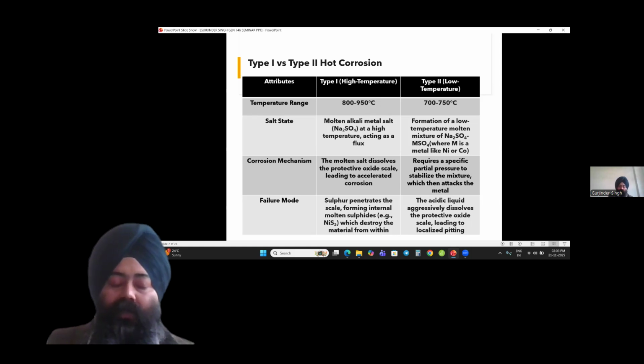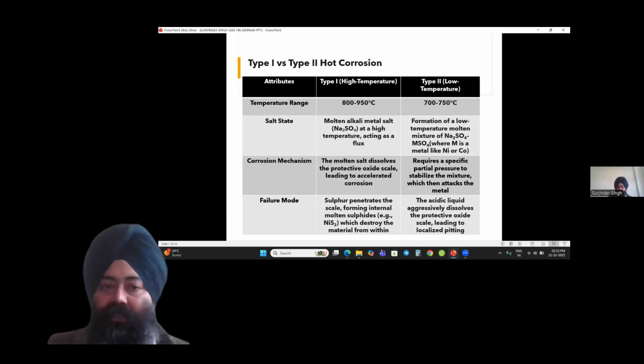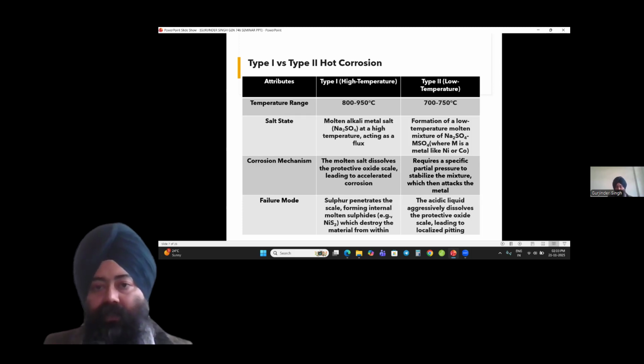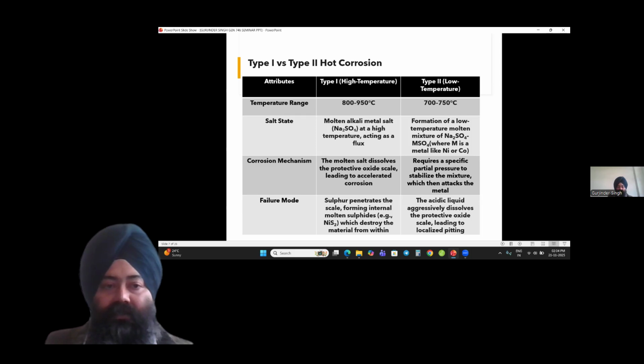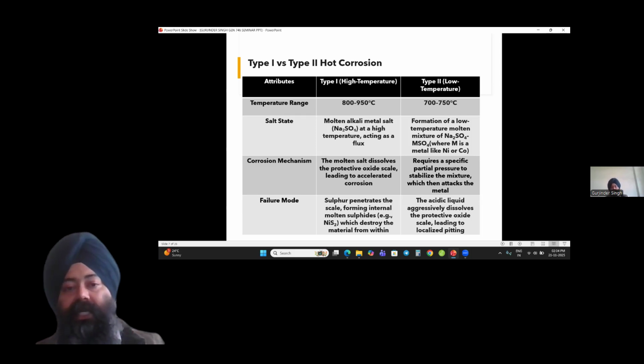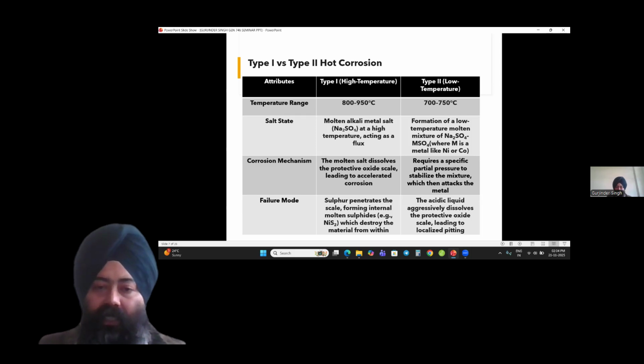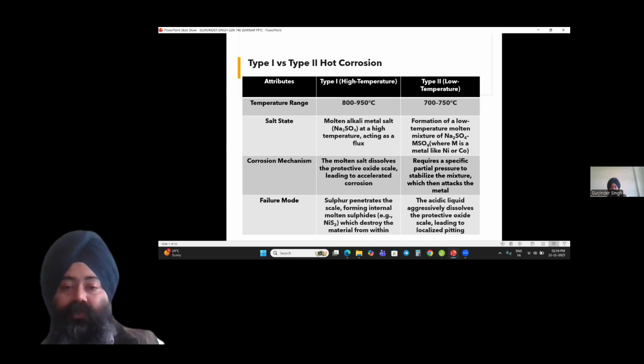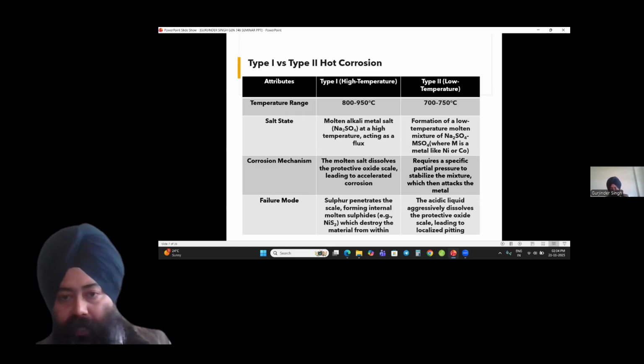Now, hot corrosion is mainly of two types, type 1 and type 2. Type 1 is basically when corrosion is done at high temperature. The temperature range is 800 to 950 degrees Celsius, and type 2 is low temperature. The low temperature range is 700 to 750 degrees centigrade. And for the salt state, in type 1, the main alkali metal salt is sodium sulfate, Na2SO4, which acts as a flux. And in type 2, there is a mixture of sodium sulfate and MSO4. M may be another metal like nickel or cobalt.